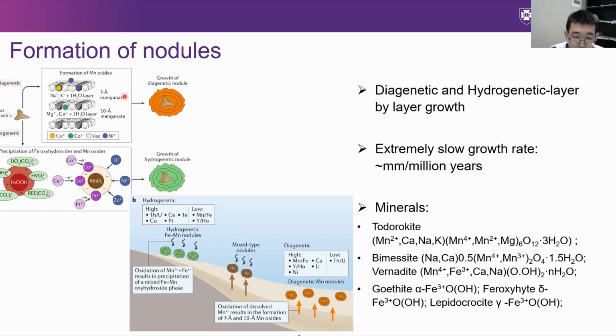In the diagenetic process, the manganese is remobilized in the sediment column and then precipitates at the sediment surface. From this process, it will produce nodules with a high manganese to iron ratio, however with a poor nickel and copper content. In the hydrogenetic process, the iron oxyhydroxide and the manganese oxide are precipitated just from the surrounding sea waters. This type of nodule usually has similar manganese and iron content, and also a relatively high grade of nickel, copper, and cobalt.